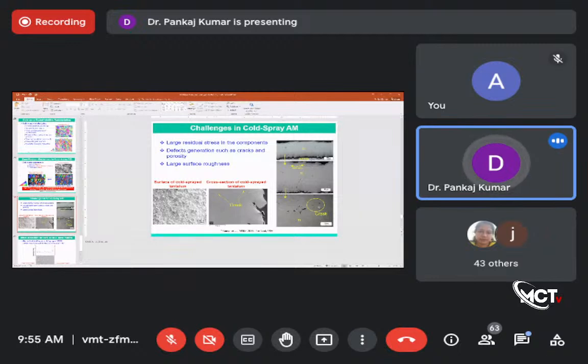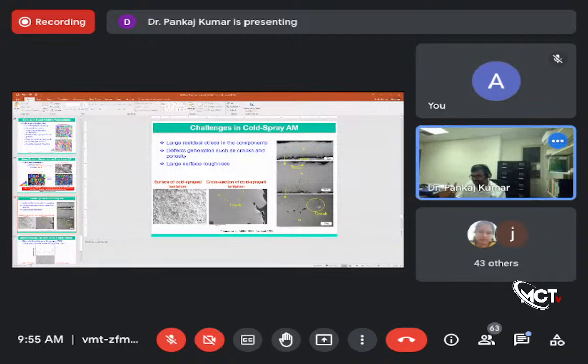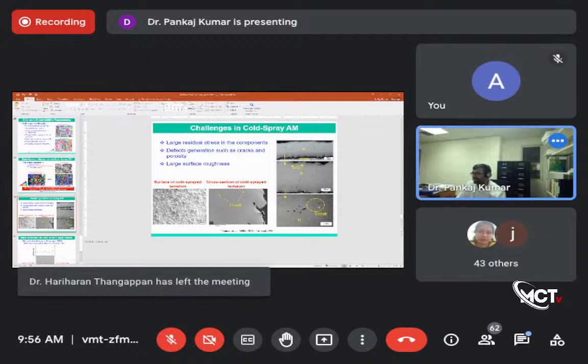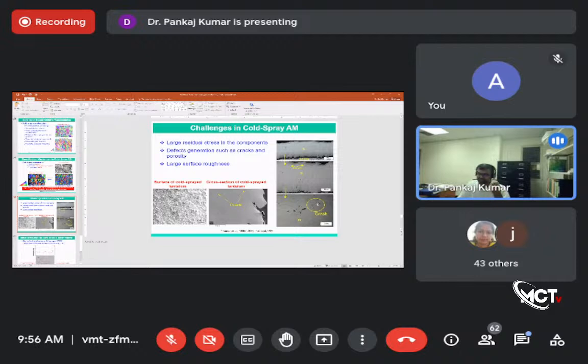So a cold spray sample, if you look at it, is a brittle sample. Even though your material is ductile by nature, after the process of cold spray, it becomes brittle. It's really brittle. It's just like glass. If you drop it, it just simply fractures. But in situ, if you look at it, you see the cracks. These cracks happen just because of the residual stress. So much strain energy goes into the process that it cracks, right? Some interfaces don't join together. It's a statistical process itself, right? So these are the challenges that we really need to worry about.